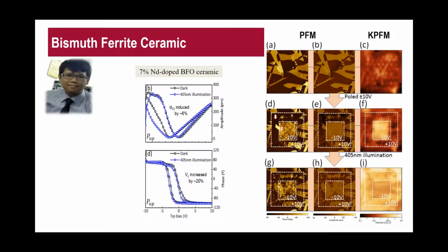So the next will be bismuth ferrite ceramic. So far, I have shown quite a number of examples in thin films. This is the first ceramic example that I would like to share with you using the PFM analytical tool. Here we show a combination of PFM and KPFM. Not only do we use PFM, but we need to couple it with KPFM to show the evidence. In PFM, we have poled the sample by providing a domain writing, and you can see it is very different compared to the pristine sample.